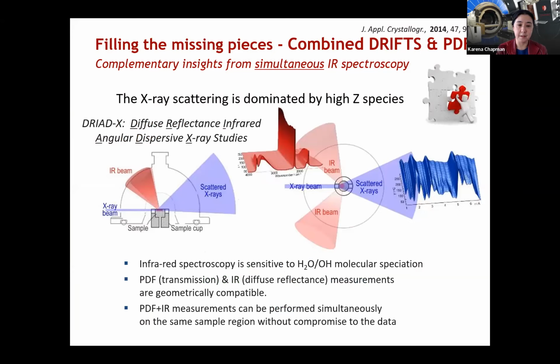This is something we can do without compromising either measurement. The X-ray scattering is dominated by the high Z species in the material, and the IR is giving us sensitive information to molecular speciation - telling us about water or OH groups that might exist on the surface of our sample that we can't see with our X-ray measurements.